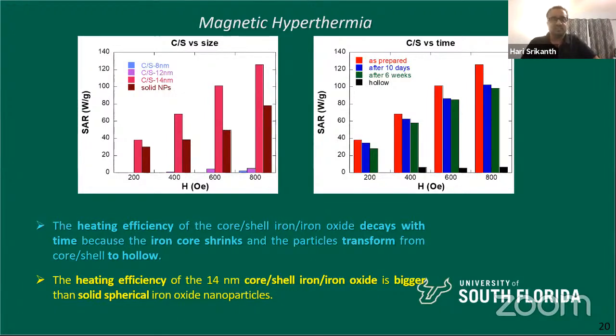SAR is much higher. However, our happiness was short-lived because as a function of time, and we don't have any control over this time because it's a process that we cannot control, over time, of course, it degrades, and when it becomes hollow, it doesn't heat up anymore. So we thought it was a great idea, but we had to discard it because of this Kirkendall effect, which is due to the differential diffusion of the metal ion versus oxygen ion. But we thought that the interface anisotropy at the core shell particle is the way to go, okay? Except that we should avoid the Kirkendall effect.